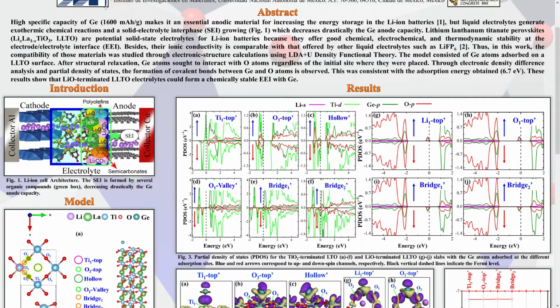Through electronic density difference analysis and partial density of the electronic states, the formation of covalent bonds between germanium and oxygen atoms is observed. This was consistent with the adsorption energy obtained, 6.7 electron volts. This result showed that lithium lanthanum titanate electrolytes with a lithium oxide termination could form a chemically stable electrode-electrolyte interface with germanium.